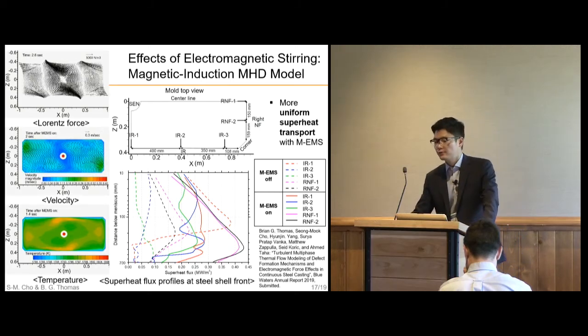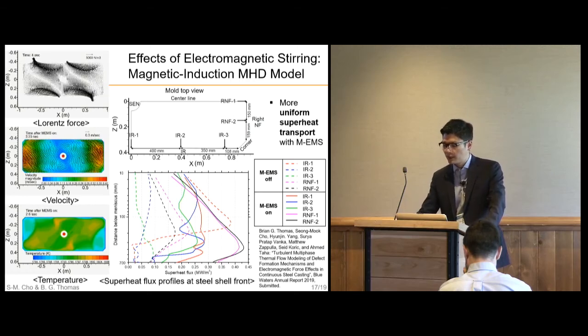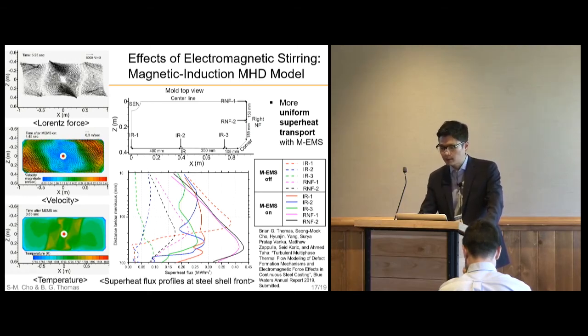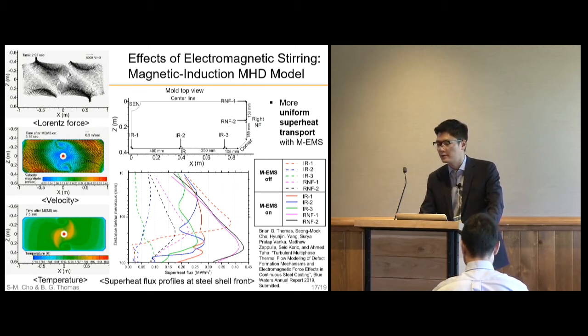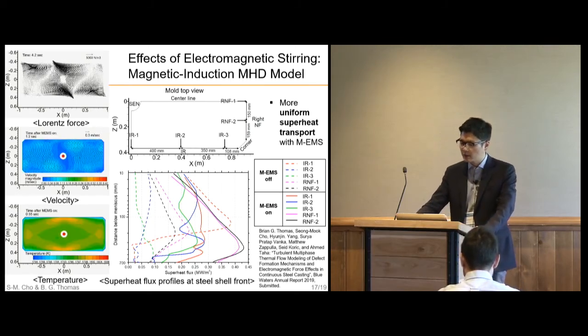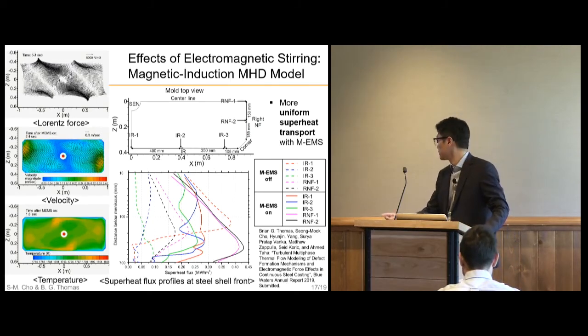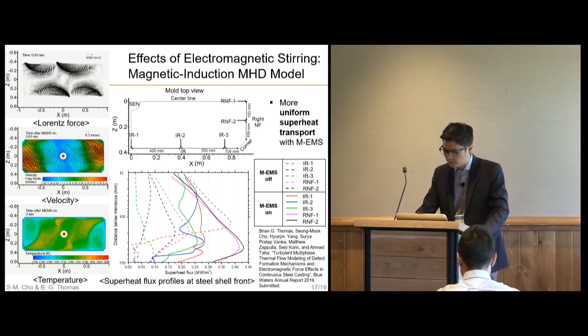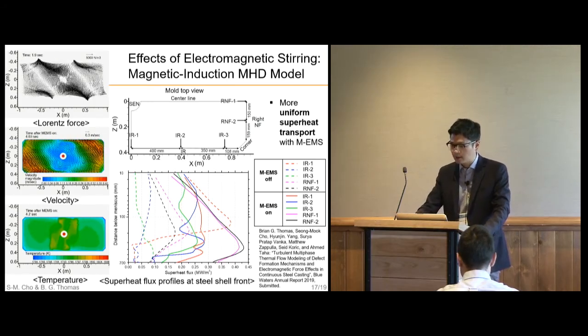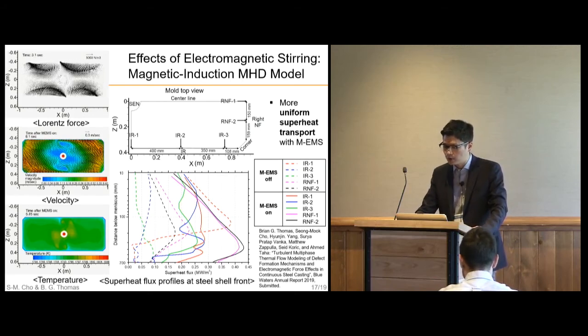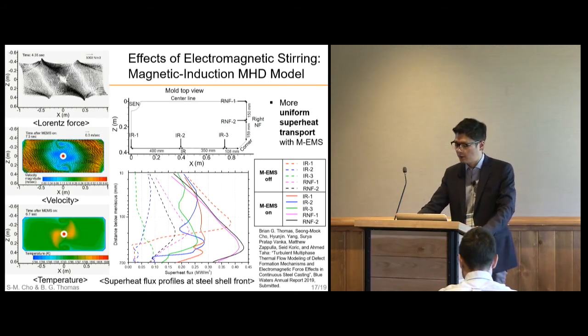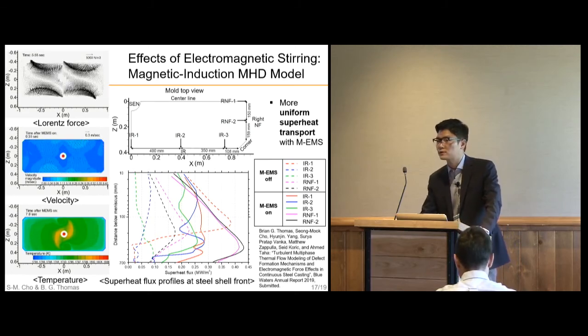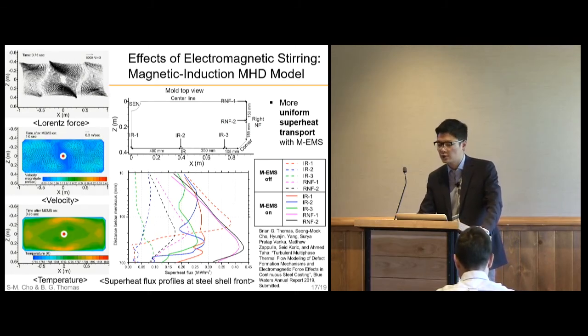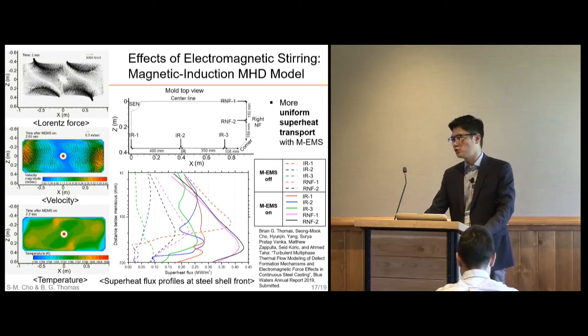So high Lorentz force around the mold wall rotates the flow near the shell front, and this steering action makes the temperature and the superheat flux more uniform at the meniscus region, including the corner regions. You can see this effect by comparing the dashed lines around the shell front with the solid lines. This effect is expected to reduce the initial solidification defects so long as the magnetic field strength is within the optimum range, which the model is being used to predict.